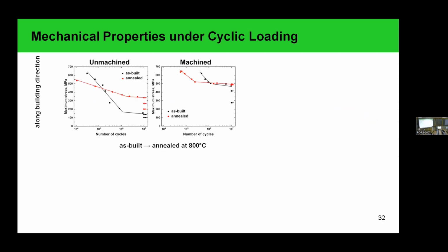Also, we analyzed the properties of our material under cycling load, and we observed what is usually observed for additive manufacturing materials: machined samples show better, higher fatigue life if we remove the near-surface defects. In the case of unmachined samples, we see a difference between the as-built and annealed samples.